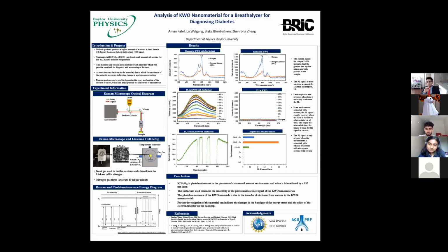So what I did is I used oxygen, nitrogen, and then ethanol, to test it with a different solvent to see the difference in sensitivity. It does interact with ethanol as well, but as you can see in the ratio, the difference is so high that we don't have to worry about that in a real world application. We also tried it with oxygen, where we have a very major decrease in our intensity, and that we propose is due to oxygen's ability to pull electrons from other things. But yes, that is just to test our material against other gases as well.